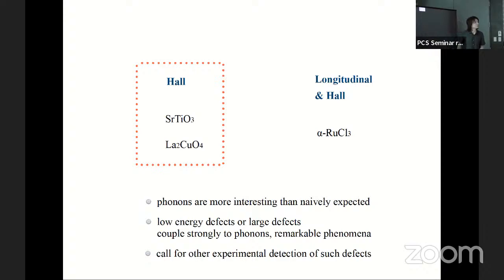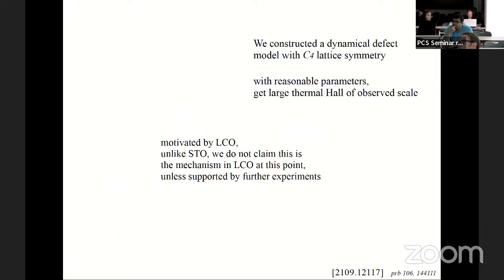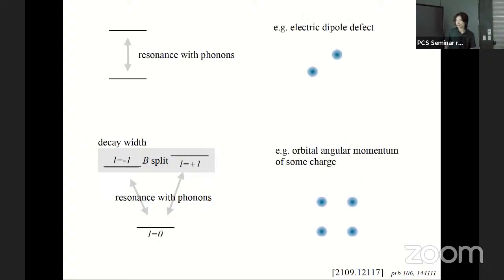Can I ask a question? I understood that in the case of STO, the defect was coming from the domain wall. Here, how do you get the defect exactly? We don't exactly know because LCO is very complicated. But you can think, for example, there is some ion whose position is not exactly at the right position that it wants to be, so that it can be at one of four positions due to the C4 symmetry of the material. If you have C4, then there should be four states? Right, there is an upper one which is irrelevant.